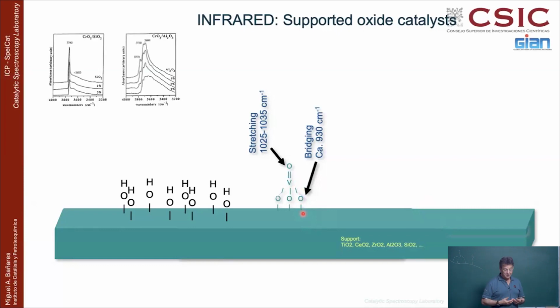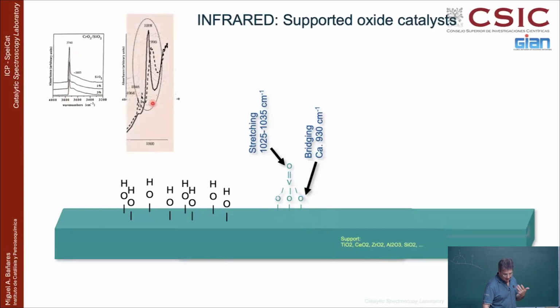And you will get these isolated species when you put a little bit, one here, one there, one there. If you increase the coverage, and of course, as you are adding it, you are consuming the surface hydroxyl groups. And when you are having this oxide, this oxo group will also show up. For instance, 1020 for vanadium, this is like 1008, which will be for molybdenum possibly, which is molybdenum oxygen double bond. But this is the kind of things that you will see with infrared.